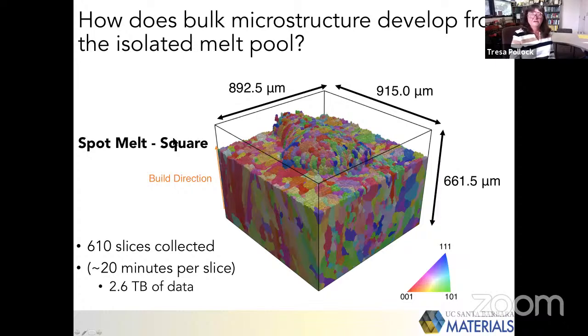Okay, so let me talk about the spot melt square setup. This was the conditions in the middle of the 3 data sets that I showed earlier. And so this particular data set has 610 slices and 2.6 terabytes of information. You can see the dimensions here. And you can see basically this data set has a structure which is much less columnar in the steady state. So this is the steady state structure. And then we've again deposited this spot.